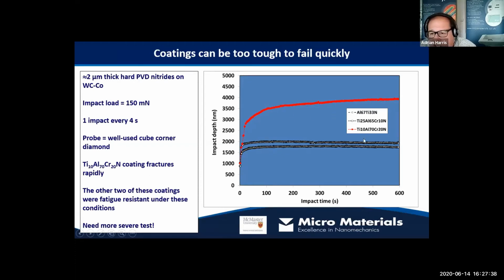And what we see in the case of the titanium aluminium nitride here with the 20% chrome, 70% aluminium, is a rapid failure. So we reach a big depth very quickly. The initial depth is similar to the other coatings, but the depth quickly increases. The other two coatings, however, the other titanium aluminium nitride and the aluminium titanium nitride, do not show a failure event in the duration of the test. They just sit there at a constant depth.